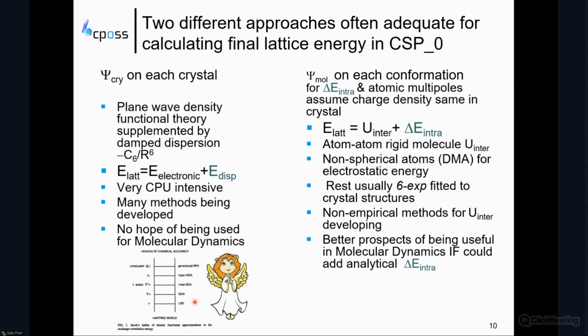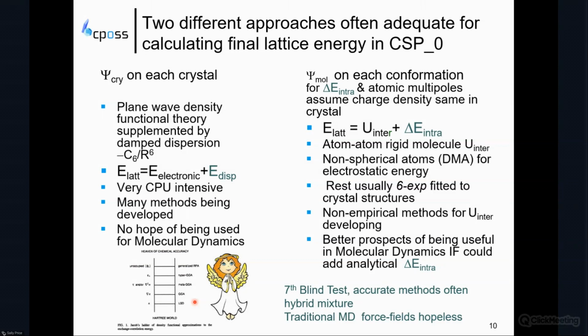But it's worth noting that in the blind test, many of the most accurate methods were a mixture of hybrids of these approaches. For example, doing extra calculations on the monomer to correct the electronic structure determinations on the crystal. And it's also perhaps worth emphasizing here that from the early blind tests, it was clear that the traditional molecular dynamics force fields were not reliable, often pretty hopeless for crystal structure prediction.